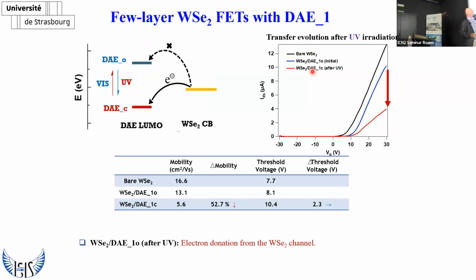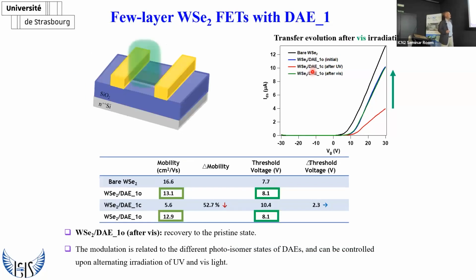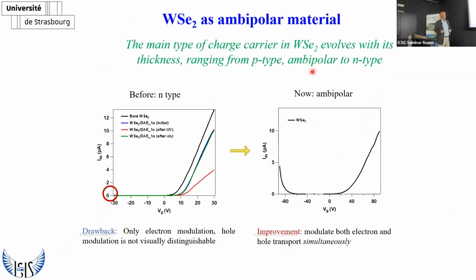Essentially what we are doing is forcing the electron to go within the band gap of our semiconductor, because that is in the closed form. And then at this point, we irradiate with visible light and we go back to the initial mobility value and the initial threshold voltage value. So we have undoped our film essentially. Now, if you play with different thicknesses, tungsten diselenide can act as an ambipolar device. And so this is what we have done.